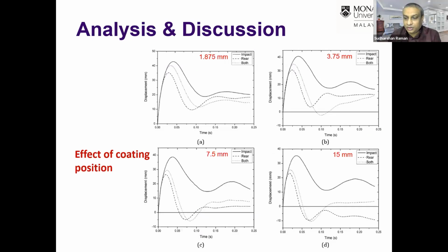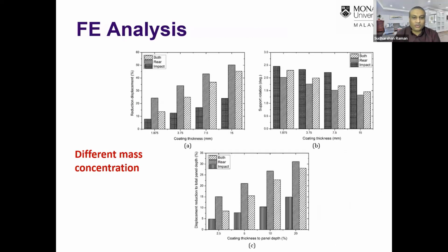Lastly, we looked at the coating position, and even for different thicknesses, we found that coating on the rear surface was more beneficial. So what we can see here is that this is looking at the mass concentration. This exhibits that the support rotation is significantly lower when you coat it on the rear surface for the same mass concentration. Reduction of displacement is higher when they are coated on the rear surface, as well as when you compare the displacement reduction due to the total panel depth. So in all cases, when you're coating on the rear face, it shows a more beneficial effect.